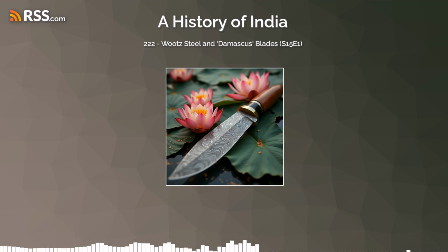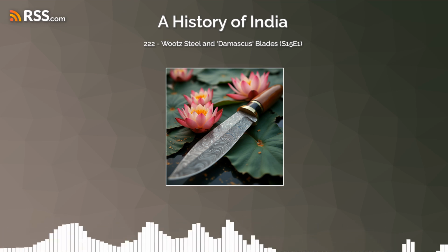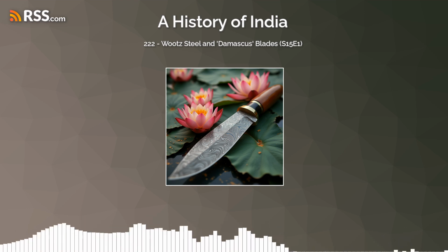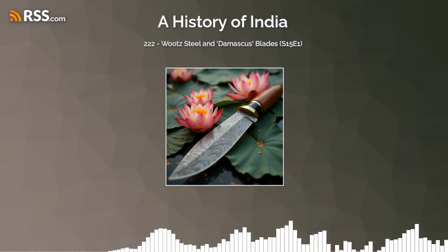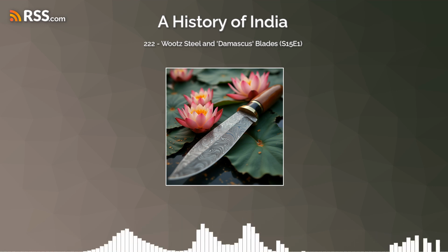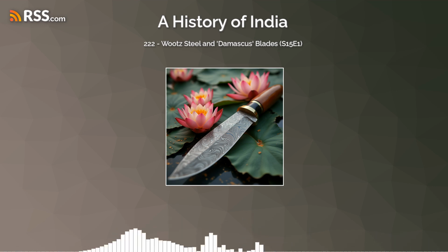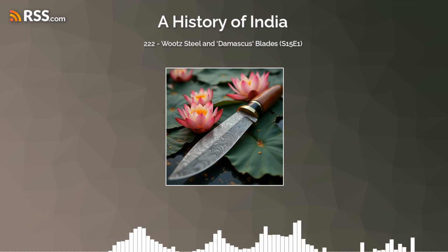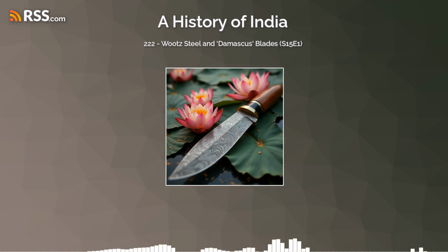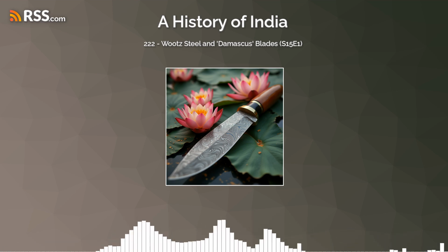Now, that cast ingot, with all that carbon and hard cementite, sounds like it would be super brittle. How on earth did ancient smiths turn that into a blade that was not only sharp, but famously flexible, too? That transformation is where the true artistry and deep empirical knowledge of the smiths, whether they were in India, Persia, or Syria, really shines. You're right, a raw, high-carbon Wootz ingot could be extremely brittle. If you just tried to hammer it out like regular iron, especially at the wrong temperature, it would likely shatter. So they had a secret technique. They had an incredibly refined technique born from generations of experience.